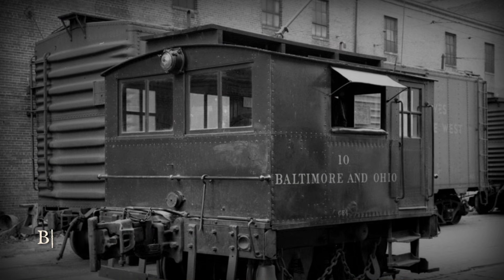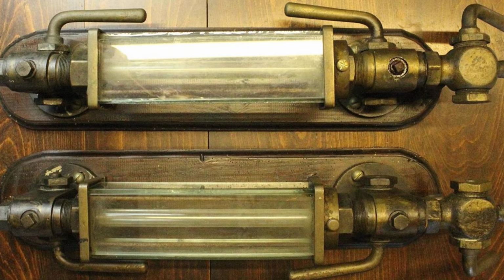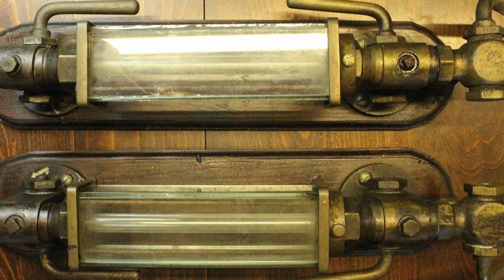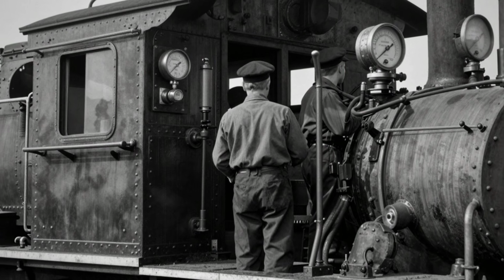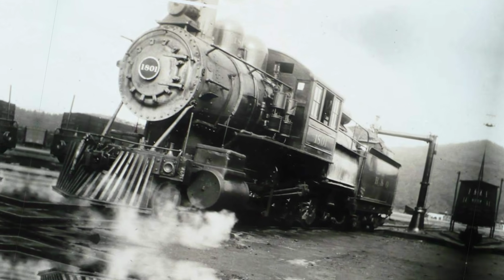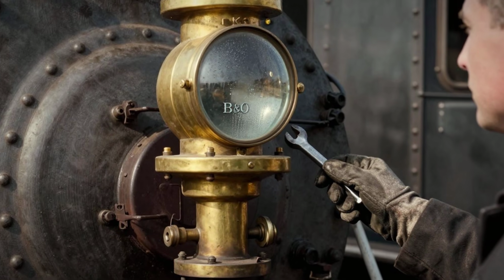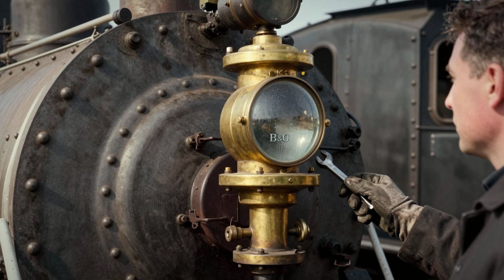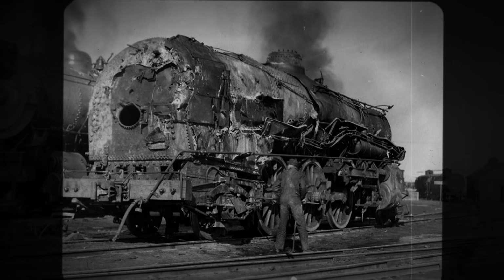No. 10, Baltimore and Ohio, 1903. The water sight glass was packed with limestone scale. The crew trusted the glass. They ran the grade blind. The glass showed a safe water level, while the actual waterline sat 6 inches below the crown sheet. Nobody in the cab had a chance.